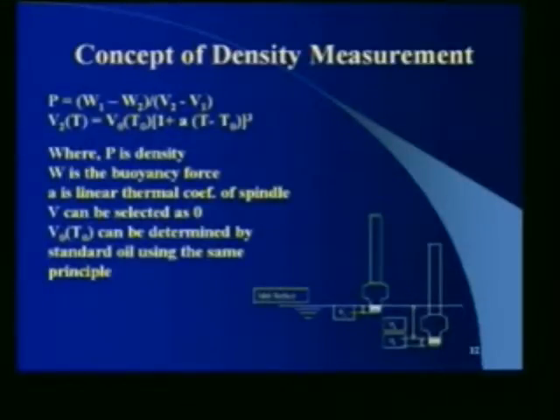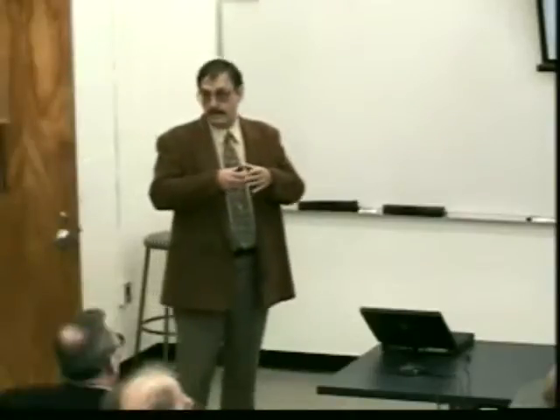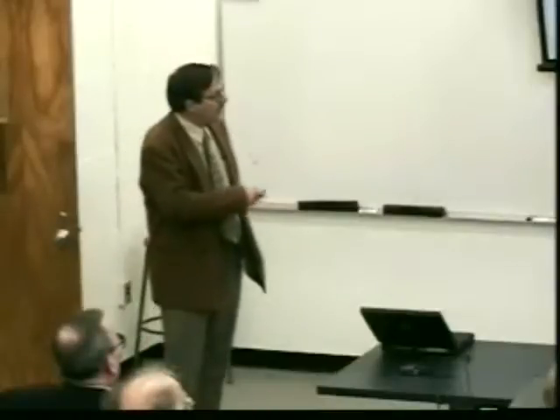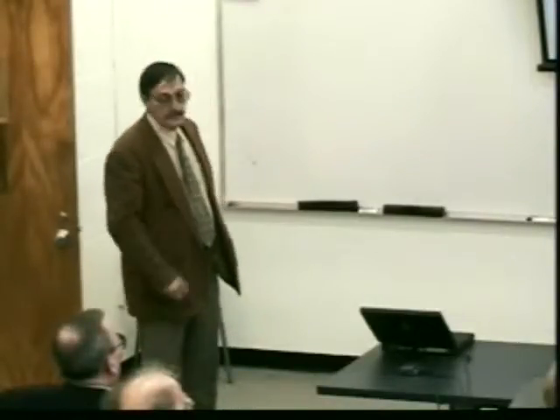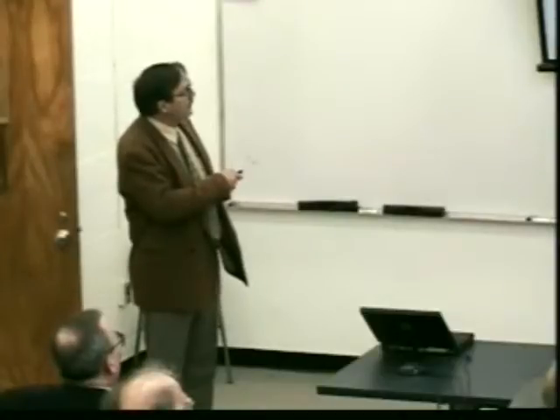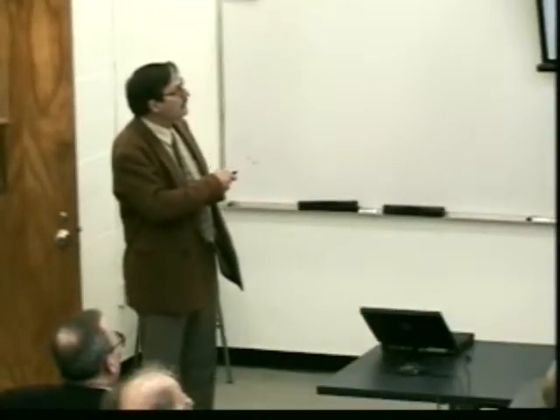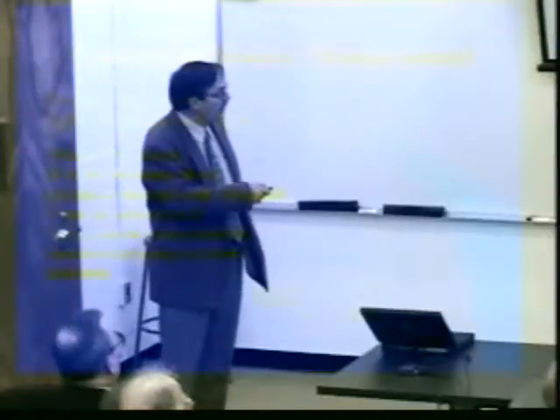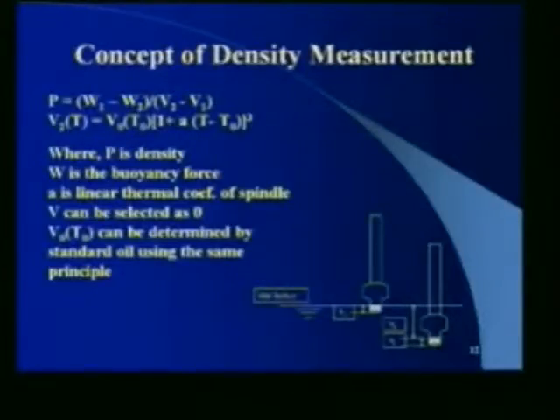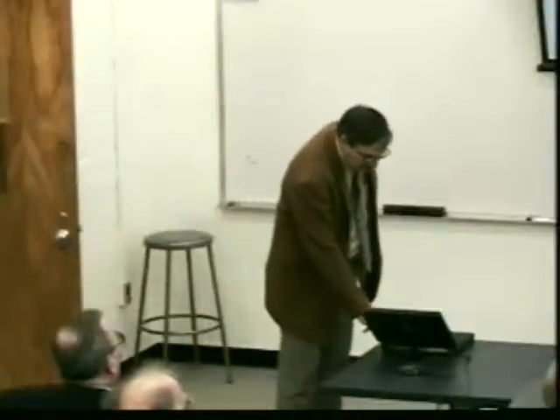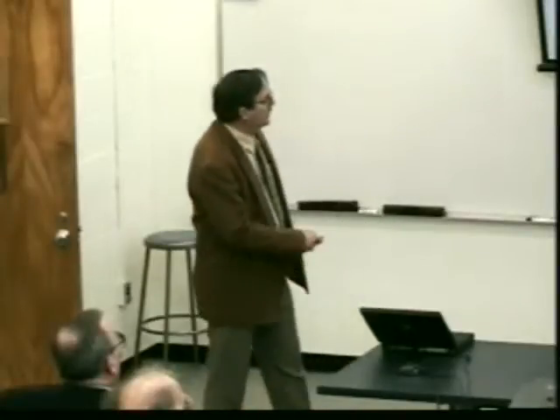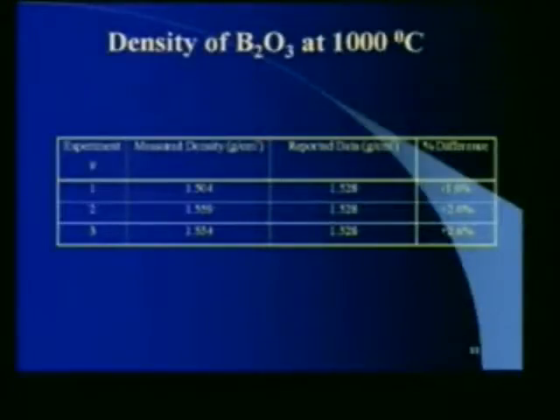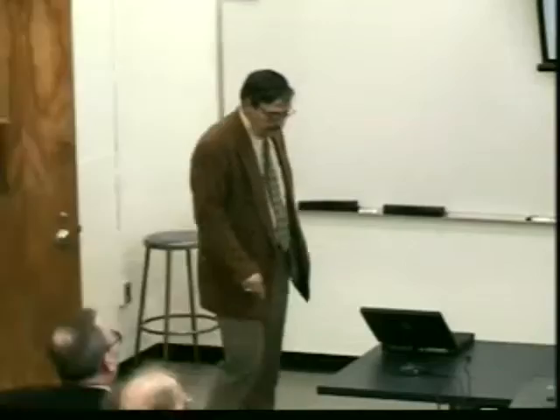And why that's important is when you have a solid in contact with a liquid, you have capillary forces by the liquid on the solid. So this allows you to subtract out the capillary forces from the measurement. The only difficult parameter is this thermal expansion, volumetric thermal expansion coefficient that needs to be known for this material in order to be able to do it. But the density then is a fairly straightforward method of weighing a plummet kind of system as it goes into the reactor. And this is an example of calibrated values for boron oxide at 1,000 degrees. These are our measured density, and these are the literature values, and they're pretty close.